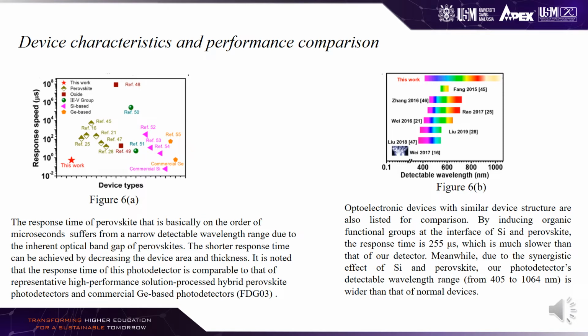germanium-based photodetectors. Figure 6b shows that optoelectronic devices with similar device structure are also listed for comparison. By introducing organic functional groups at the interface of silicon and perovskite, the response time is 255 microseconds, which is much slower than that of our detector. Meanwhile, due to the synergistic effect of silicon and perovskite, our photodetector's detectable wavelength range from 405 to 1064 nanometers is wider than that of normal devices.